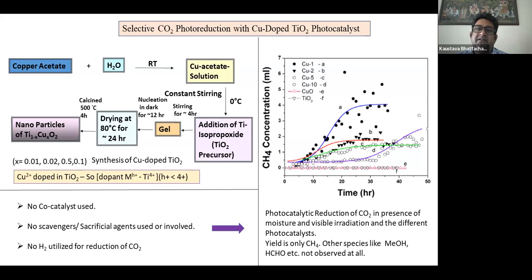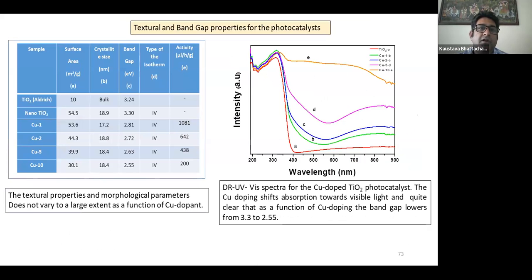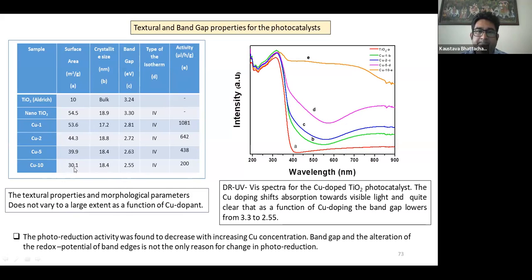Okay, so what we find is that upon doping copper in the titanium, the lower the amount of doping, the more methane was being produced. If we check the overall textural parameters, we find that as a function of copper doping, the band gap obviously goes from 3.2 to 2.5. However, the production of methane was the other way around. So copper 1 has more methane produced than copper 10. So we tried to understand why that was happening.